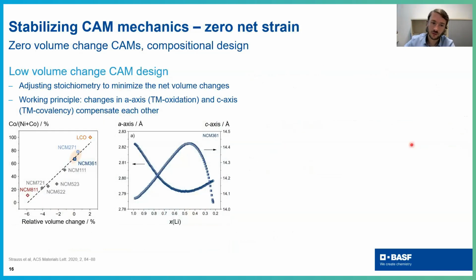Now, if you switch a little bit to the mechanics of the cathode active materials in solid state batteries, there are different volume changes which cathode active materials experience, and they are plotted here depending on the nickel to cobalt ratio. You see here different NCM materials and also LCO, and there's a line which is quite straight, and you have, let's say, positive volume change for LCO, and you have a negative volume change of NCM 811, which is nickel rich material. So this is during the charge, during the delithiation.